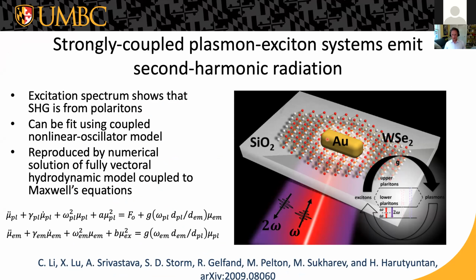So here we are using these gold nanorods. Instead of coupling to quantum dots, we coupled to a monolayer of tungsten diselenide. These transition metal dichalcogenides, especially tungsten diselenide, have narrow linewidth and excitons that are stable at room temperature and have very large oscillator strengths. And the gold nanorods give you fields in the vertical direction, normal to the surface, that line up with the transition dipole moment of those excitons. So this kind of configuration has been used several times already to show strong coupling at the single particle level, the single particle here meaning a single metal nanoparticle, to excitons inside TMDs.